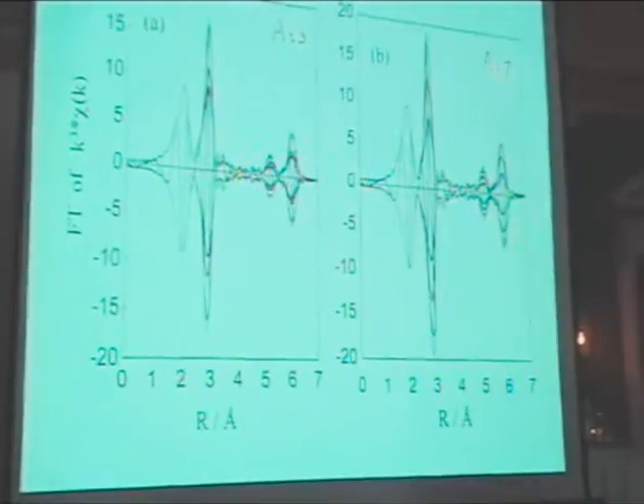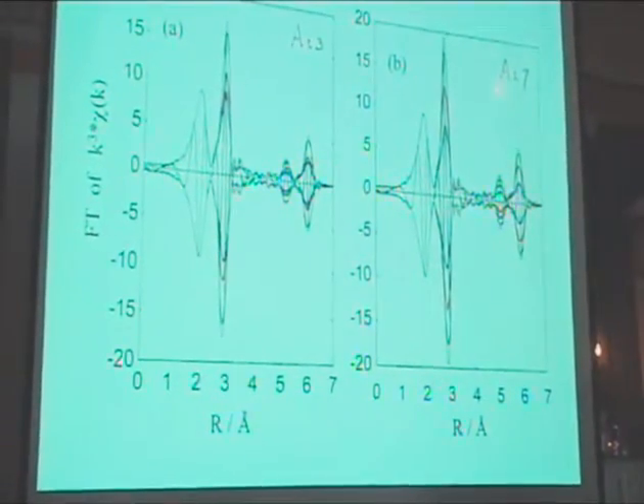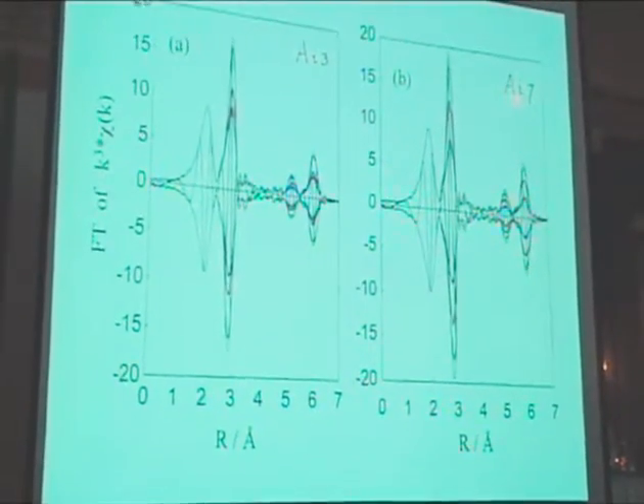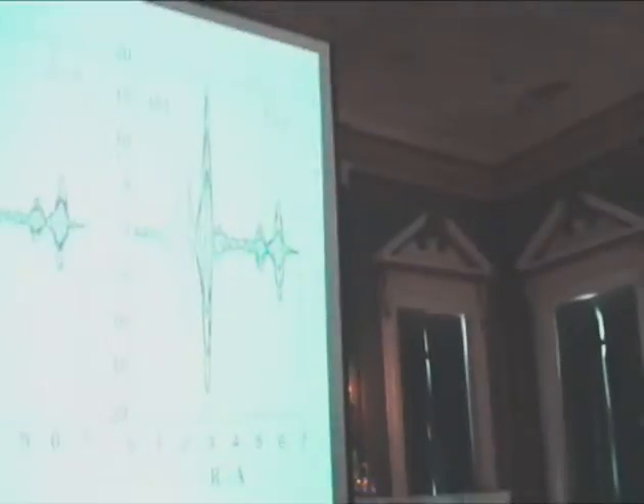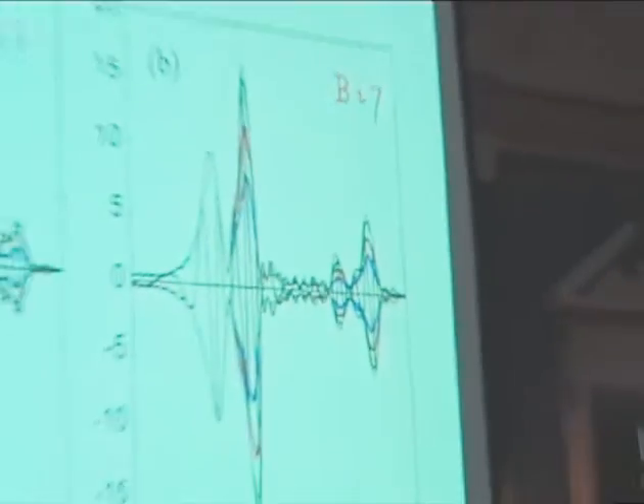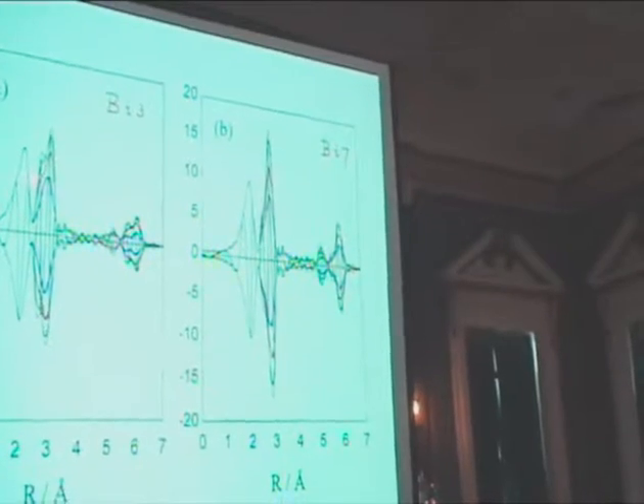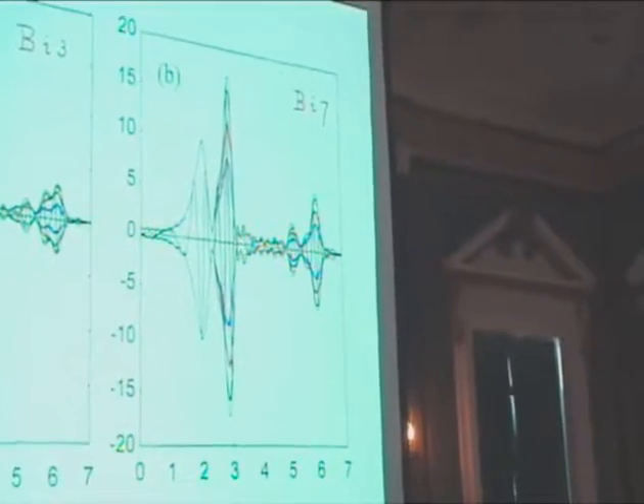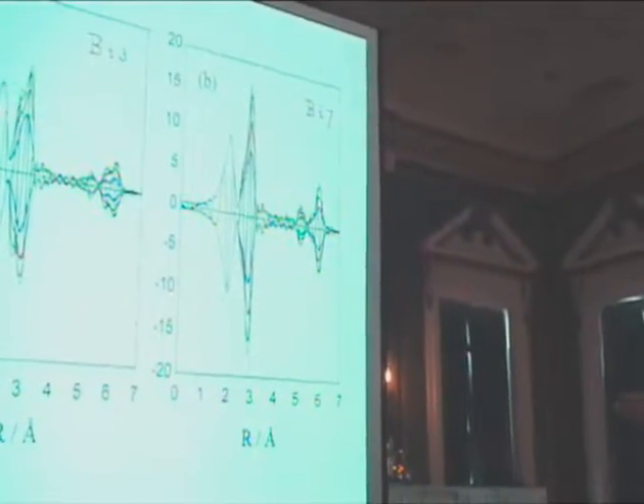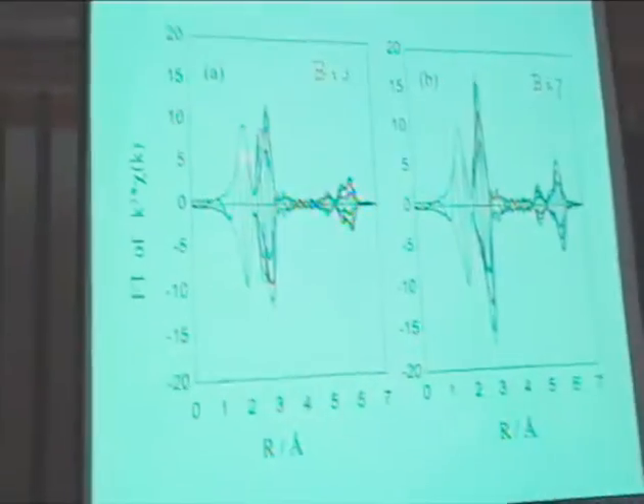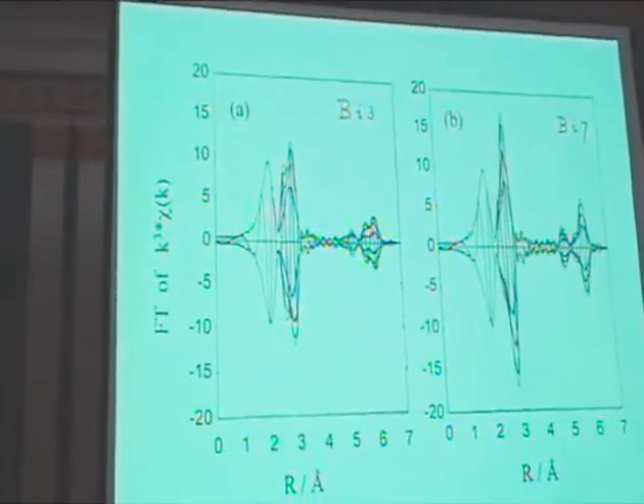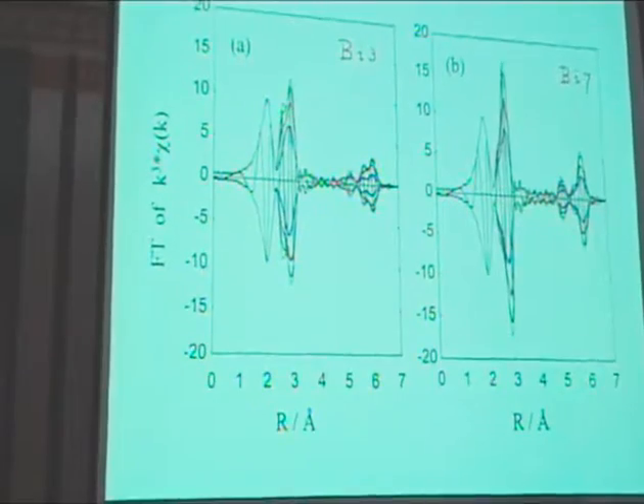When you do that with, at the one edge, a quite strong contraction, you see that, oh sorry, this is the other model. I must go to the next one. Oh, it's here, that's the B model. You see that you do get this second peak then, you can distinguish it. But we never saw it in reality. So this means we have overdone it. We have introduced a shortening which is too strong, otherwise we should have seen it in the experimental spectrum. So this cannot be the truth.